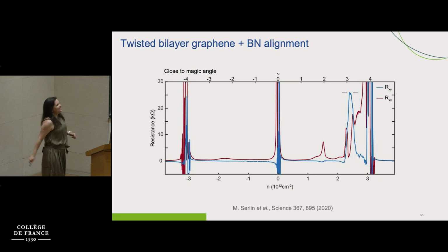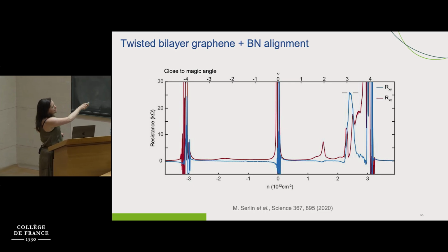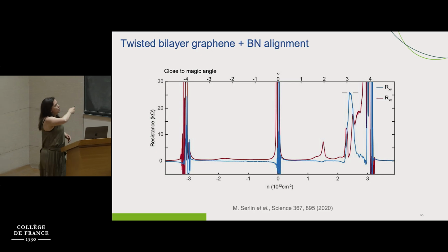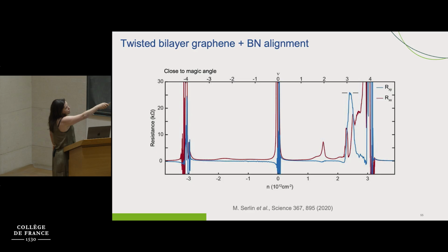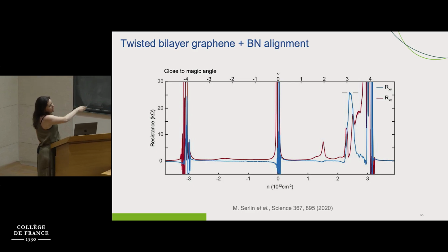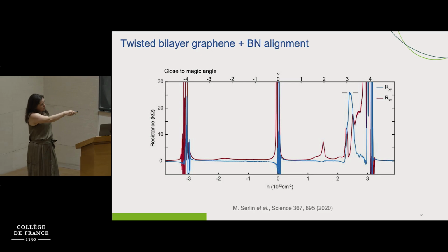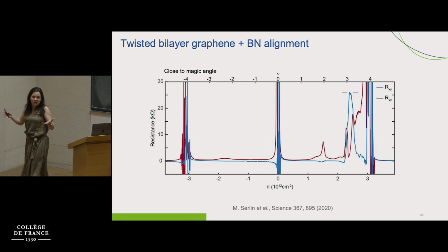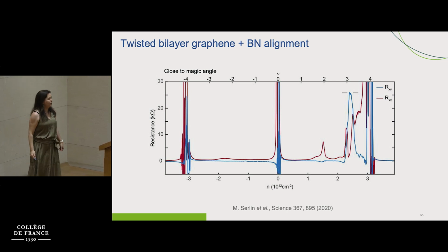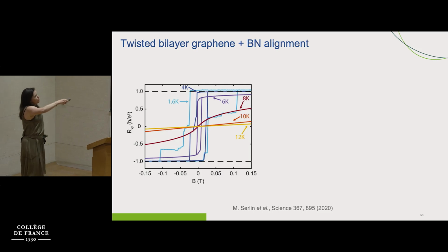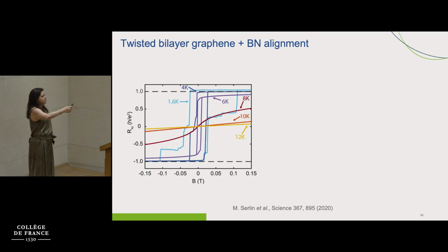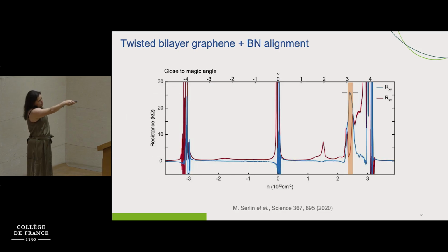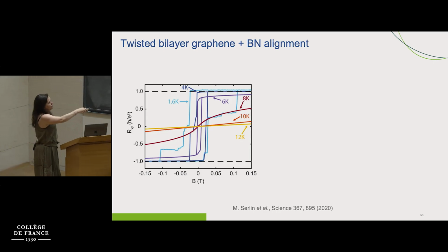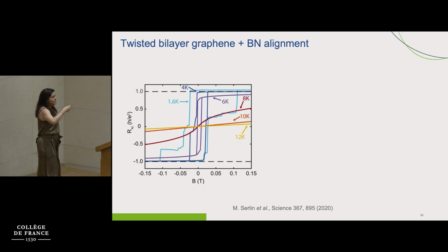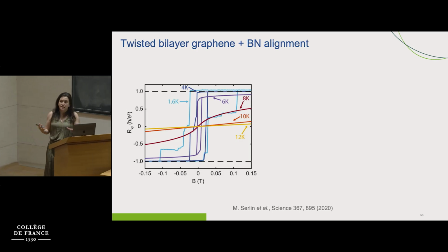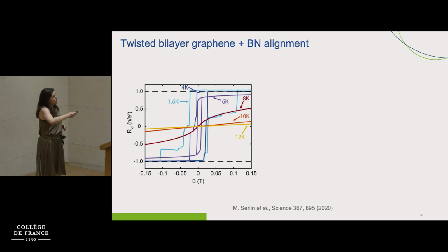So let's see those results of the quantum anomalous Hall effect. When we measure the resistance as a function of the density in a quantum anomalous Hall state, what you're going to see is that for zero magnetic field, you have a strong increase of your Hall resistance, and this value is going to be quantized. At the same time, you're going to see a decrease in the longitudinal resistance. So exactly the same as the quantum Hall effect, but this time without any magnetic field, okay? If you place your Fermi energy at this position, with your gate voltage, and you sweep the magnetic field back and forth, you're going to see these hysteresis loops.